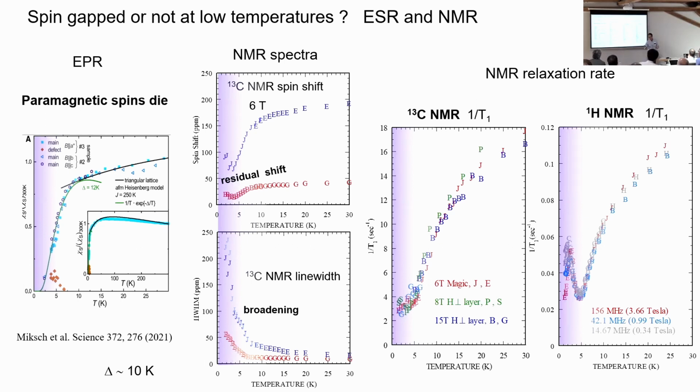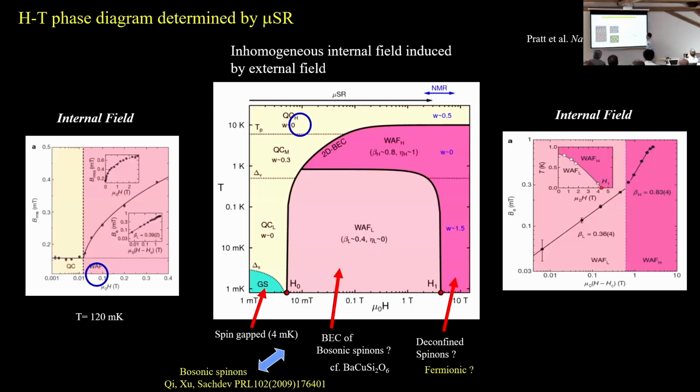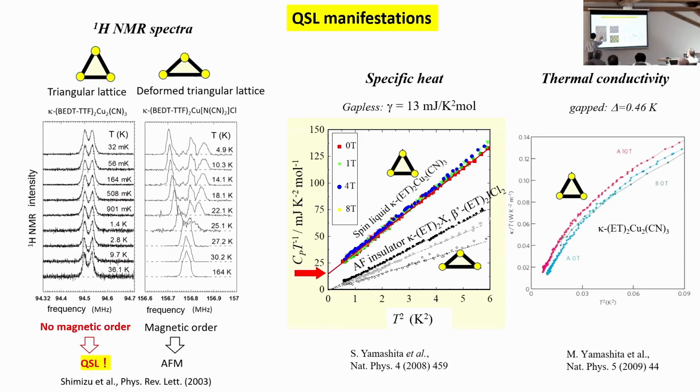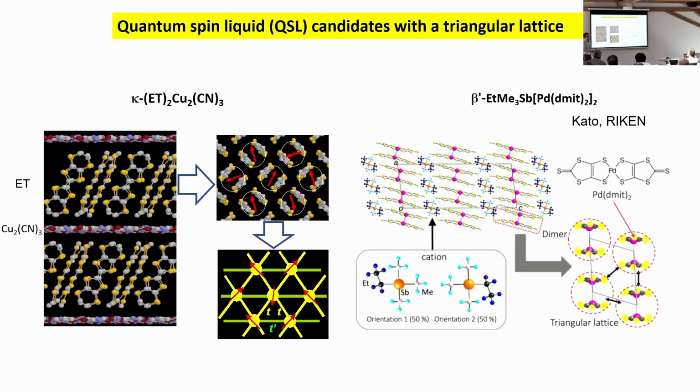Hydrogen is a very subtle problem, because the hyperfine coupling constant is very small. However, the dipole coupling becomes more significant than at the carbon site. So the form factor of Q is very different. I mean, it must be different because you're getting a different temperature dependence.